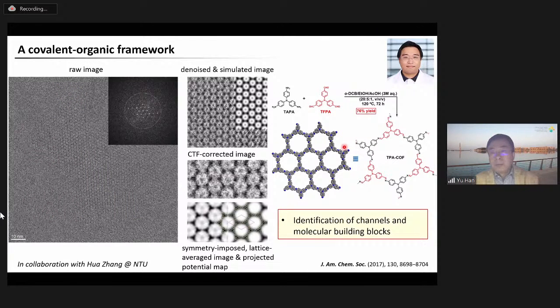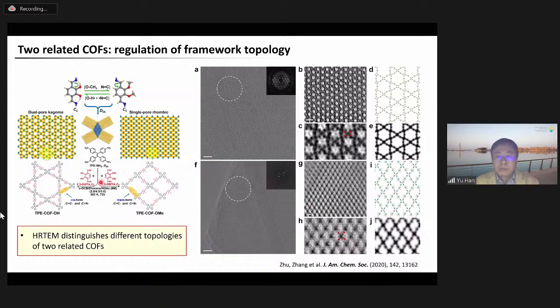As mentioned earlier, our method is not limited to imaging MOFs, but also other sensitive materials. Due to the time limitation, I just quickly show you a few examples. In 2017, we imaged a TPA-based COF. COF stands for covalent organic framework. This COF has a 2-dimensional hexagonal structure, and we identified 1-dimensional channels and the molecular building blocks in the image. Earlier this year, we used this technique to distinguish different topologies of 2 related COFs due to the presence or absence of the intramolecular hydrogen bonding. Either dual pore Kagome structure or single pore rhombic structure can be obtained from 2 otherwise totally same synthetic systems.